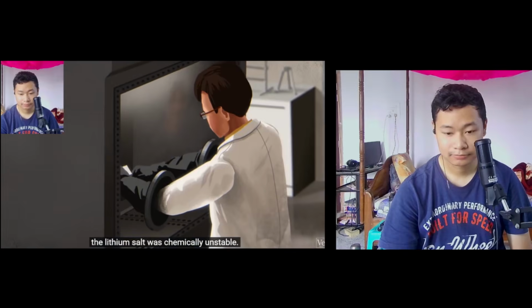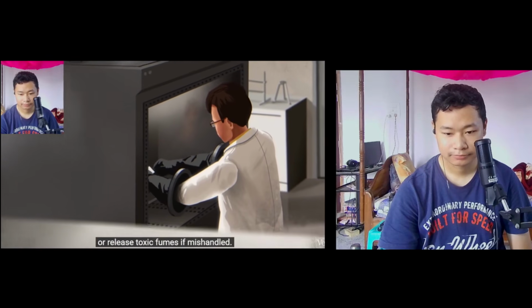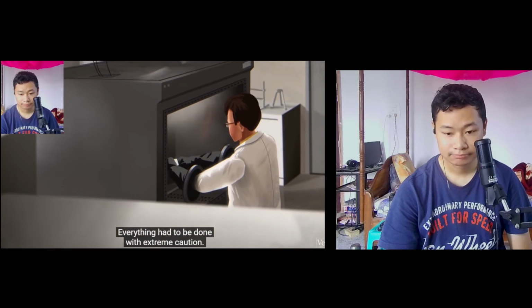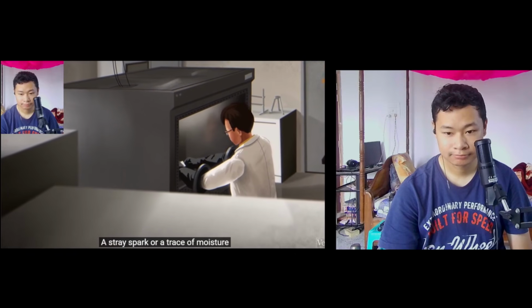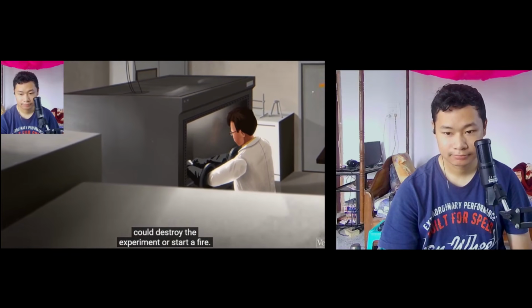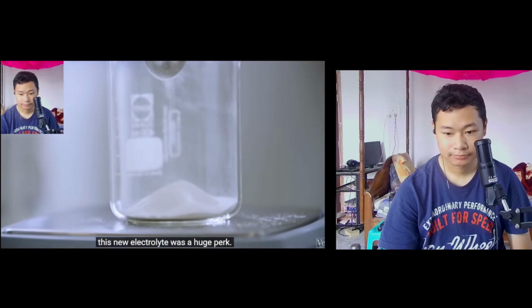But it came with serious risks. The solvent was volatile, the lithium salt was chemically unstable. Together they formed a mixture that could explode or release toxic fumes if mishandled. Everything had to be done with extreme caution. A stray spark or a trace of moisture could destroy the experiment or start a fire. But if you could get around the danger, this new electrolyte was a huge perk.